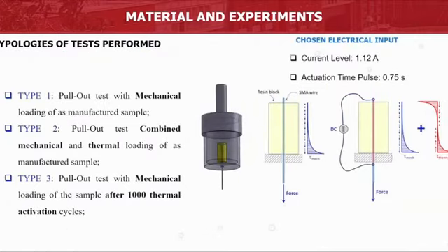We have performed three different types of tests. Type 1 is a pull-out test with a pure mechanical load on the manufactured sample. Type 2 is a pull-out test in which there is a combined mechanical and thermal load, both applied at the same time. And the final one is the pull-out test with a pure mechanical load, but compared with type 1, there are first 1000 thermal activation cycles. The chosen electrical inputs are a current level of 1.12 ampere and an actuation pulse time for each cycle of 0.75 seconds.